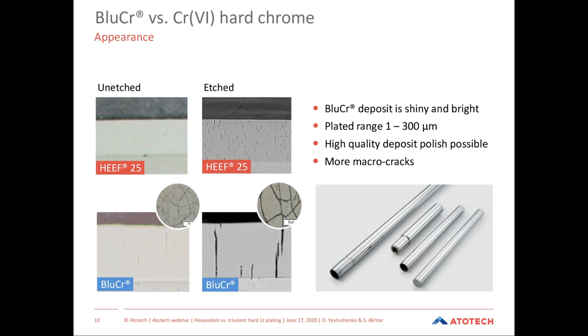In both cases, we can achieve thicknesses from 1 to 300 micrometer. Also, we are able to achieve high quality deposit with adapting some polishing facilities so that we have comparable results for hexavalent and blue chrome layers at the end. The big difference is that the layer deposited from blue chromium bath has more macro cracks.